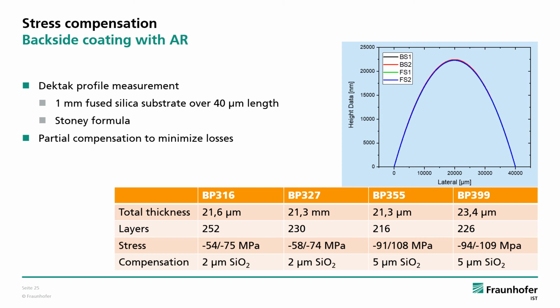We measured the profile of 2 fused silica substrates with a thickness of only 1 mm at a Dektak system over a range of 40 micron. You can see some measurements of one example in the graph on the right side. From the maximum height value, we calculated the stress for all coatings using the Stoney formula. It was in the range from 50 to 80 megapascal for the zirconia-based filters and in the range of 90 to 110 megapascal for the tantalum-based ones. We decided to not fully compensate the stress to minimize the losses and apply 2 micron silicon oxide for zirconia filters and 5 micron for tantalum filters.